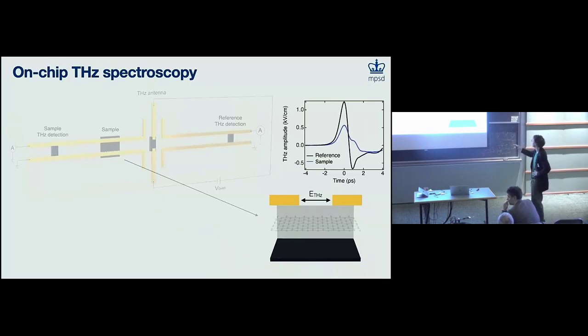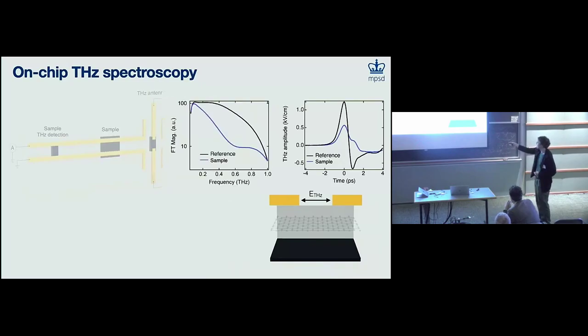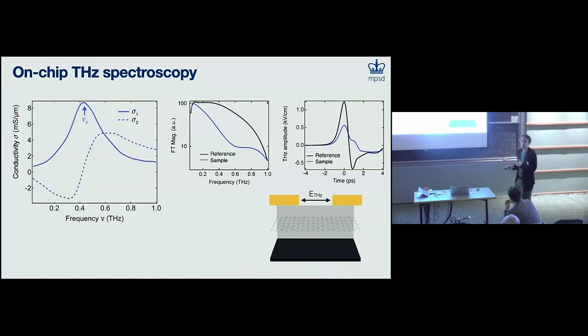This is the amplitude in field, and this is the time. But you can see the pulse that went over the sample is dramatically reduced in amplitude, and there are additional dynamics that show up. Now, the way we extract the conductivity of the sample is basically the same as in far-field time-domain terahertz spectroscopy. You Fourier transform these two signals, and we get something that looks like this. Then you take the ratio of these, multiply by some constants, and out pops both the real and imaginary part of the optical conductivity. Now, what you will notice here...